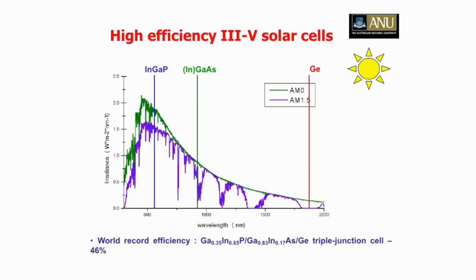So here's a case where we use three different materials, and we stack one on top of the other. This material absorbs this part of the solar spectrum, this material absorbs this part of the solar spectrum, and this material absorbs the other part of the solar spectrum, so that's why you're able to get efficiencies as high as 46% or so. In fact, we have been working on some of these material systems. And what we're doing is asking how we can reduce the cost.